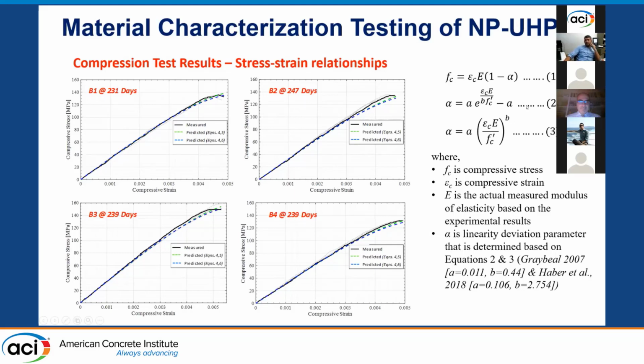But we have done this and we get at least the early part. This is non-confined UHPC and we didn't really care that much about capturing the post-peak behavior. So we just wanted to at least get the initial part, which says something about the Young's modulus indirectly. The equations, for example, that Graybeal and the folks at the Federal Highway have proposed for estimating the full stress strain relationship in compression up to the peak. So we show that this works for non-proprietary UHPC as well. And we did some assessment for the equations here.